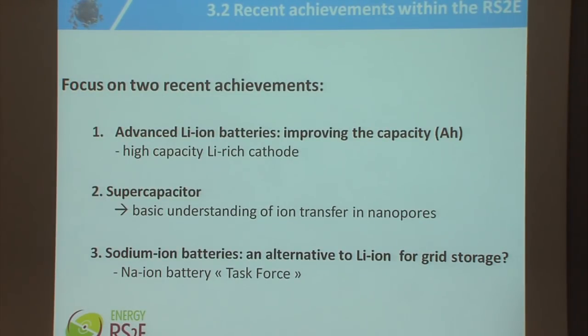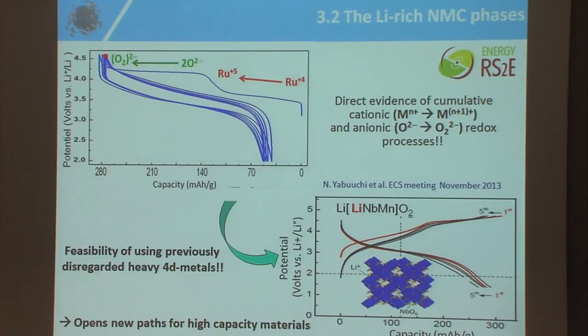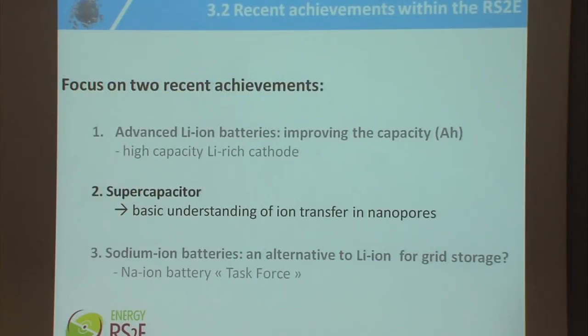on batteries. The first one, advanced lithium ion, you saw that. This is the redox mechanism that Jean-Marie Tarascon at Collège de France discovered by playing not only on the cation oxidation state, but also with oxygen oxidation state. You can increase the capacity of materials. So that's really something which is in the next future, which is going to be very important. And the key issue to solve here is the stability, cyclability. You can go up to 280 milliampere hour per gram. You can double the capacity.